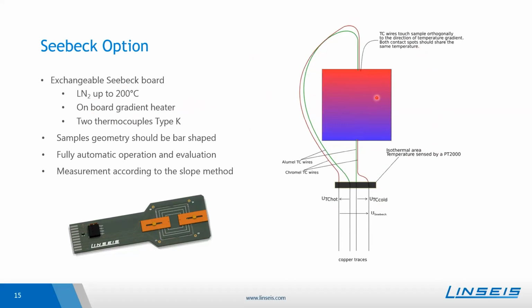So we have the sample, and we have several thermocouple wires which touch the sample orthogonally to the direction of the temperature gradient. Both contact spots should share the same temperature, which is realized by placing the sample thermocouples really close to each other. We use an alumel thermocouple wire as well as a chromel thermocouple wire. Ideally, the sample is bar-shaped so that it fits into these contact pads, and the complete measurement will be automatic in respect of the operation itself and the evaluation.